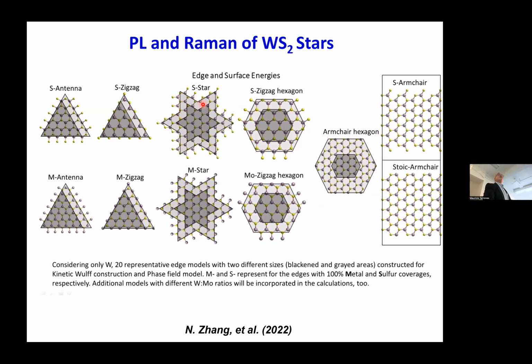But here, in the case of the stars, let's say one peak of the star is metal terminated, the other peak is sulfur terminated. Metal terminated, sulfur. So that's what we have here in the star shape. So this shape is controlled by controlling the metal to sulfur ratio during the growth. That's right. And using low sulfur concentration.